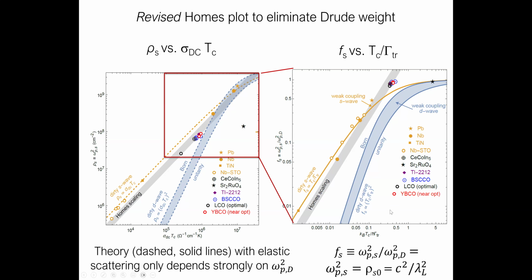So David and Steve went back through the literature, looked for all the optical data they could find, and put as much data as they could on this plot with the new scaling variables. Initially, with the data that we have from the Holmes plot, and including strontium ruthenate, it still doesn't look very good, with the exception maybe that strontium ruthenate could be described as a weak coupling D wave. But we still don't know what's going on.